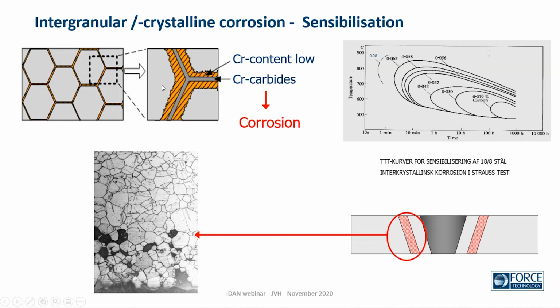If you say we have like 18-20% chromium in the grains here as the average composition, then we might get as low as 10 to 12 in this area. So obviously very much less resistant. And we have two ways to avoid that, or in fact we have three. If we can weld fast enough so that we don't get so many carbides, then we also reduce the sensitive areas around them. But if we don't, we will have a situation like this, where grains would fall out due to corrosion along the grain boundaries. Or we could reduce the carbon content.